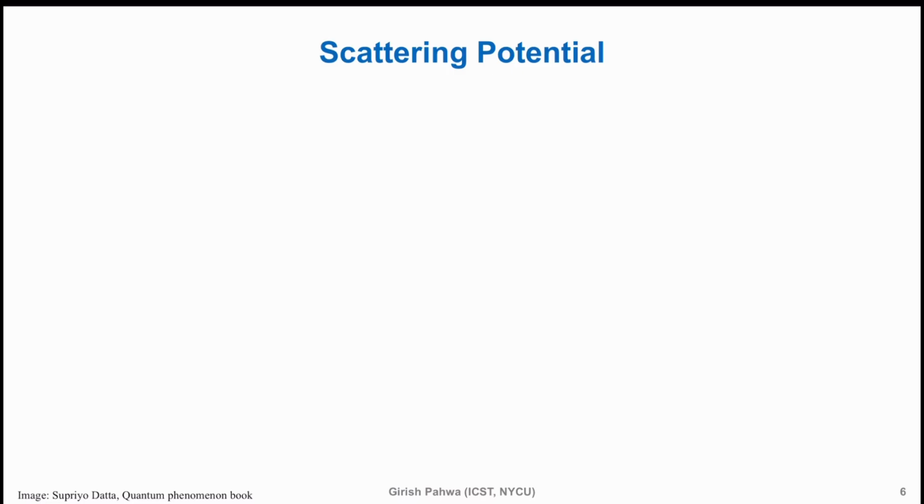It will have a different potential and it has a positive charge. So it will create some deformation at that local point. And that becomes the scattering center. When does the scattering happen? Whenever I have anything different from the perfect periodic potential, I will have scattering.